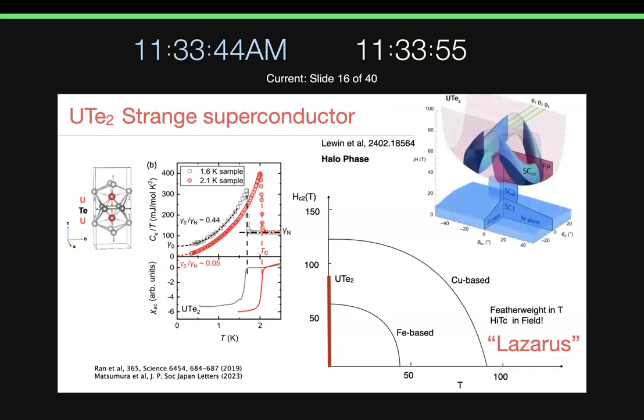Okay. And this is the phase diagram of this system. This is no longer just an arXiv. The group that's been working on this is very good at coming up with great names, and so they call this the halo phase. And the reason it's called the halo phase is that around the b-axis, you can actually follow the superconductor all the way around. This is a re-entrant superconductor. In this system, it already has a very large upper critical field for its Tc. You can see that this is the upper critical field hovering between 10 and 20 Tesla in these different directions. But along the b-axis, there is this column of superconductivity that extends up to a first order phase transition where the spins finally lock together in a parallel configuration as a first order metamagnetic transition.